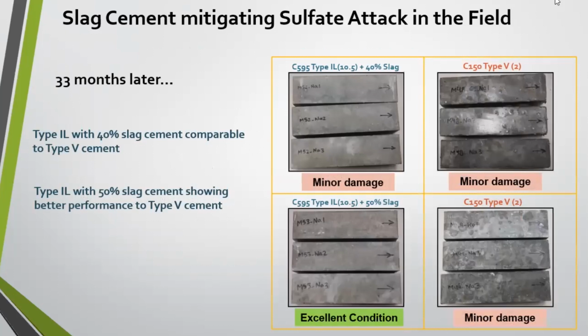So this is from 33 months later. And as you can see, most all of these had minor damage, including the type IL with 40% slag, which fell in line with the type 5 cement. But just bumping it up to 50% slag under these conditions, and we've got excellent condition on all of these samples. So finding that right concentration of slag cement, you get great benefit from even a little, but understanding where those guidelines are and having that testing in hand will give you a great indication of what you need to use to manage any potential sulfate attack.